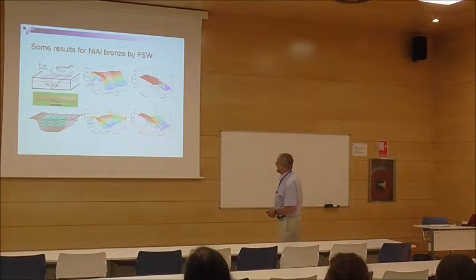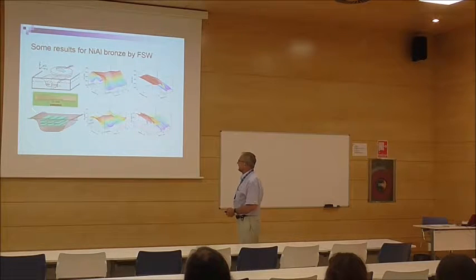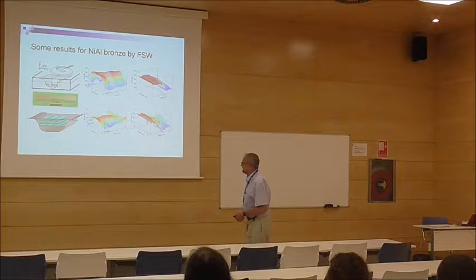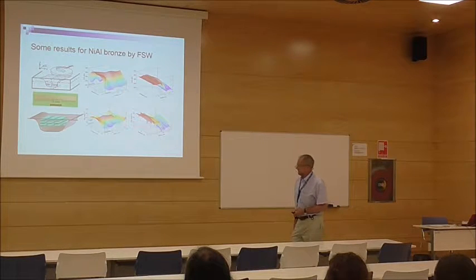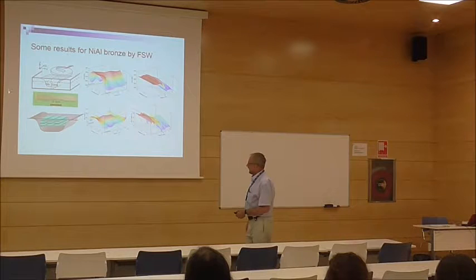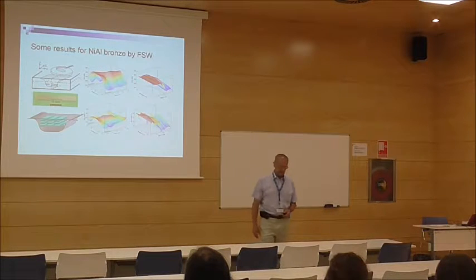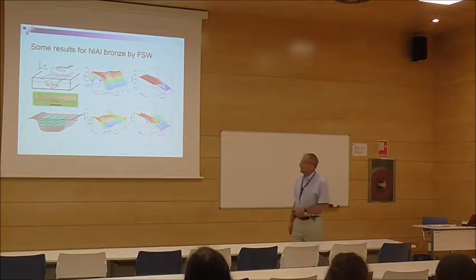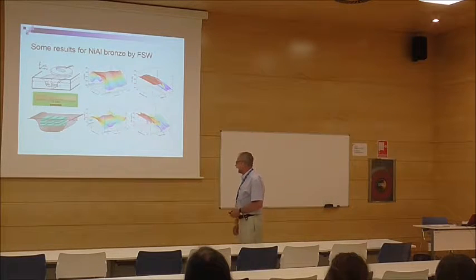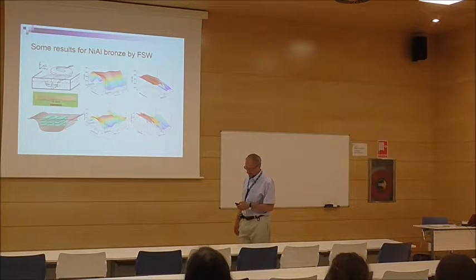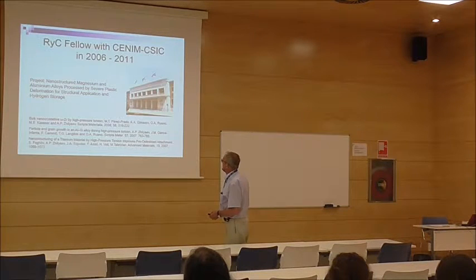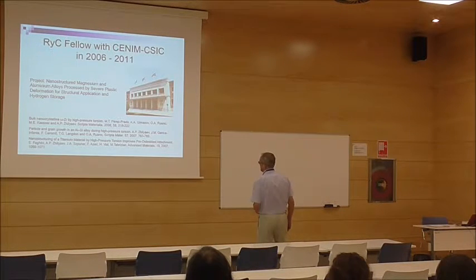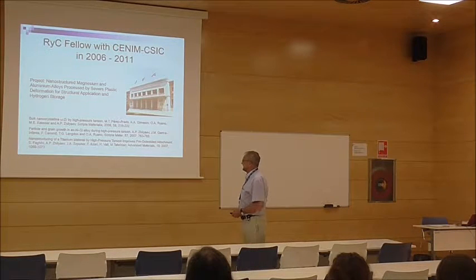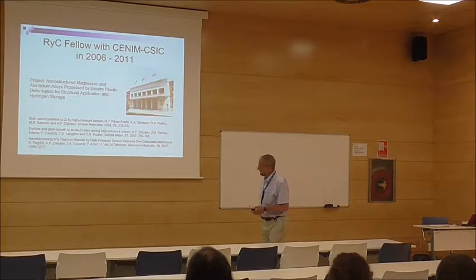So we published quite good papers there, very strong ones, and we actually worked on the stir zone of friction stir welded bronze, where we made miniature samples to measure the mechanical properties. Actually, it was measured by mapping micro-hardness, and of course it's consistent with micro-hardness mapping, but it's just trivial tensile properties. So this is CENIM, it's in Madrid, you know where it is. And during this stay I also published quite a nice paper, including with Teresa.